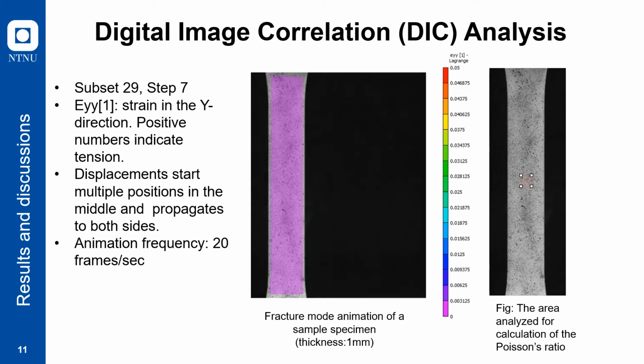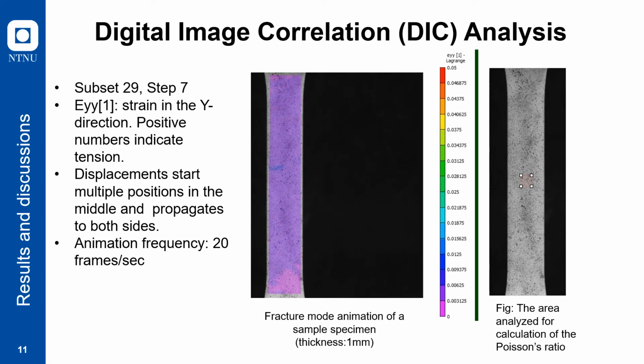And as you can see, the label here, EYY, means the engineering strain along the Y direction. As we play the animation here, as time goes by, there is some deformation in the middle part of the specimen, and it propagates to both sides. Then when it reaches some point, it goes to a different color, which means the strain is getting larger, and then it will have the largest strain showing here, which means this is the area that's most likely to get broken. And these are the methods of calculating Poisson's ratio. For the DIC, we can select one small area somewhere in the middle, and we can do the calculation for the Poisson's ratio.